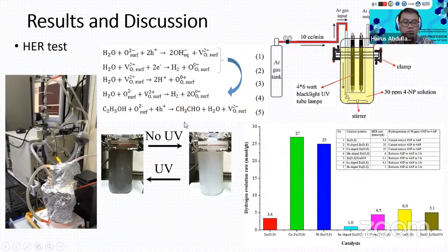But in this case, we try to make the efficiency higher. So that's why we also add the hole scavenger, such as ethanol. And ethanol will also create more oxygen vacancy sites. As the oxygen vacancy sites increase, there is more absorption of water molecules and more protons, which can finally be reduced to hydrogen. Then the efficiency of the hydrogen evolution reaction becomes higher. Okay, so this is the specific setup in our lab for this hydrogen evolution reaction.